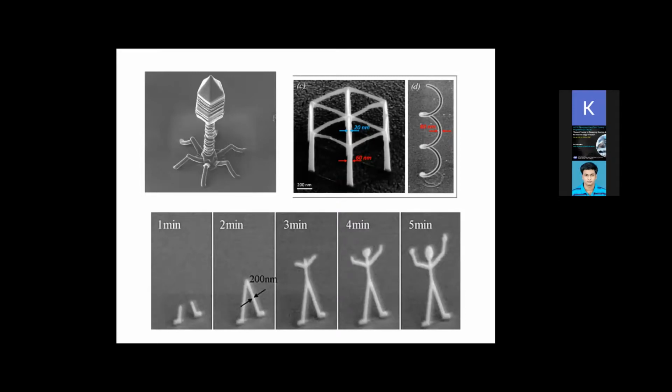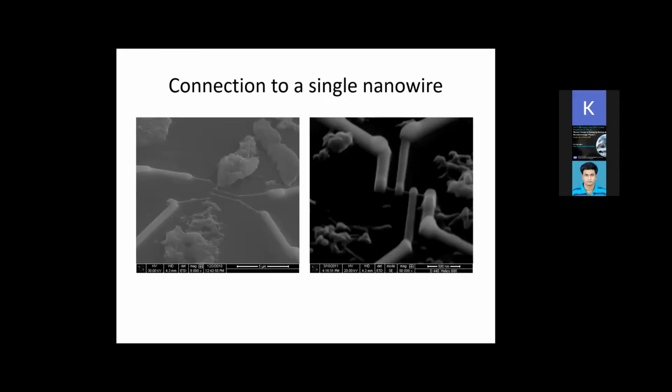So that is a main disadvantage. If you think that you are depositing a pure platinum, no. It's actually a composite of carbon and platinum, where carbon is amorphous and platinum is crystalline platinum in an amorphous carbon matrix.